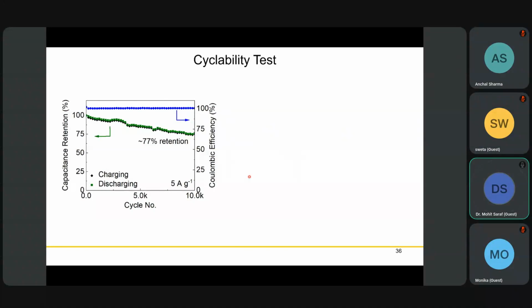After doing cyclic voltammetry and charge discharge experiments, we do a cyclability test to check the cycle life of your system. Typically, for publication purposes, we usually run 10,000 cycles, but for supercapacitors like carbon material based ones, we can run over 1 million cycles. It should be noted that while reporting capacitance with number of cycles, it is also important to mention the Coulombic efficiency.